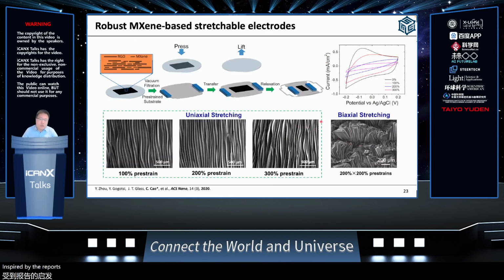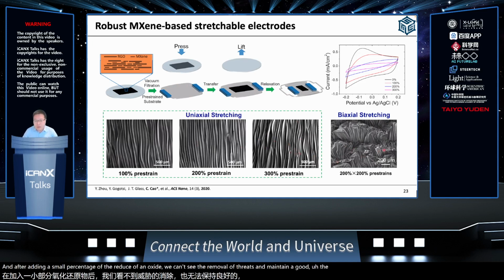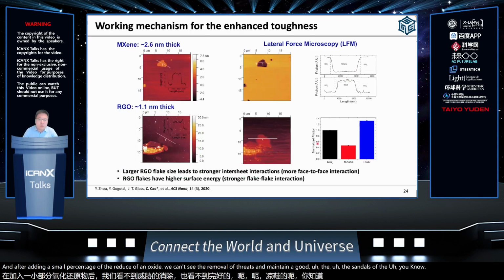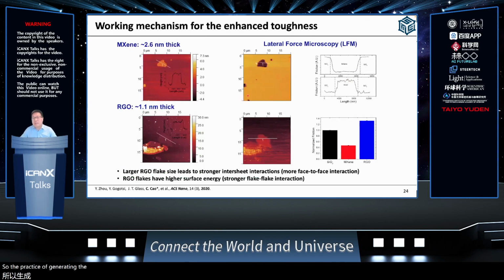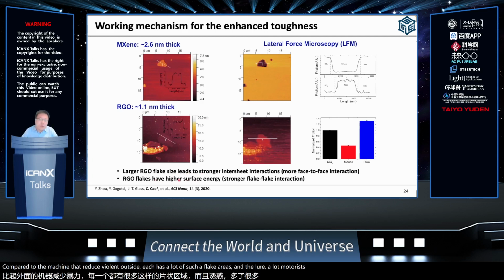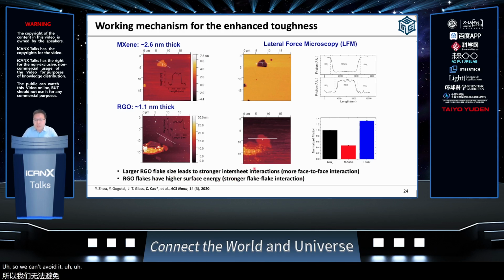Inspired by reinforced masonry in civil engineering, here we added reinforcement to MXene with reduced graphene oxide. After adding a small percentage of reduced graphene oxide, we can completely remove the cracks and maintain good standards of the electrodes. The cracks generated in the relaxation process are attributed to the high mechanical modulus and the small flake size of the MXene film. Compared to MXene, the reduced graphene oxide has large flake areas and a lower modulus. It also has a high surface energy, so it can increase the face-to-face interactions.